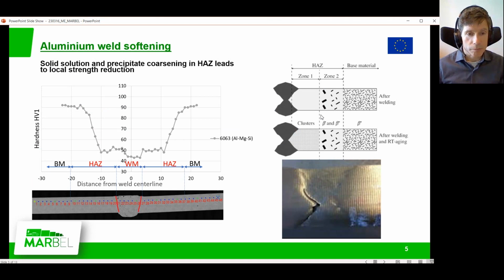This is caused by what is called solid solution. During the heating of the weld, if you see in the right picture here up, the precipitates that have been created in heat treatment are in solid solution again, and further away from the weld, the precipitates have been coarsening. So they grow and coarsen, and both of these zones 1 and 2 are weaker than the original material. We can see it in the picture to the left here, which shows measures of the hardness, which represents the strength of the metal.